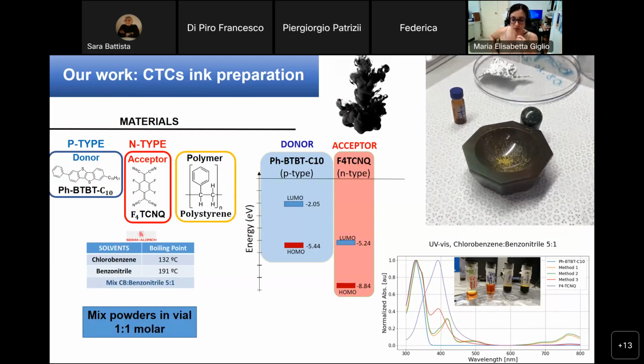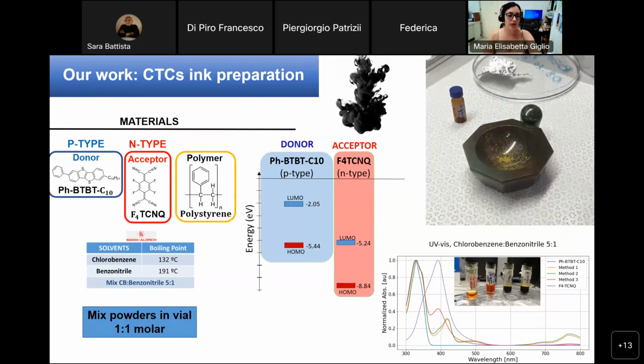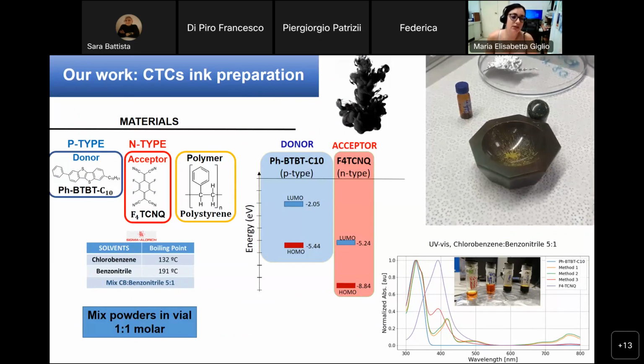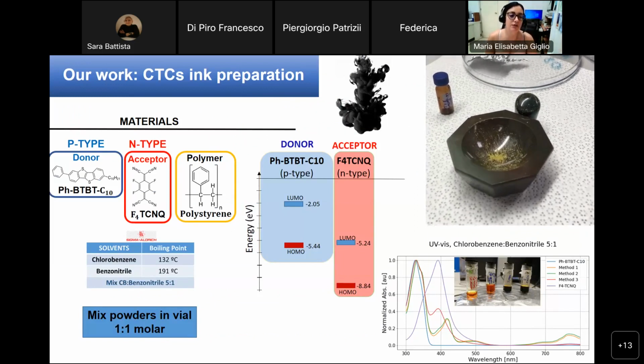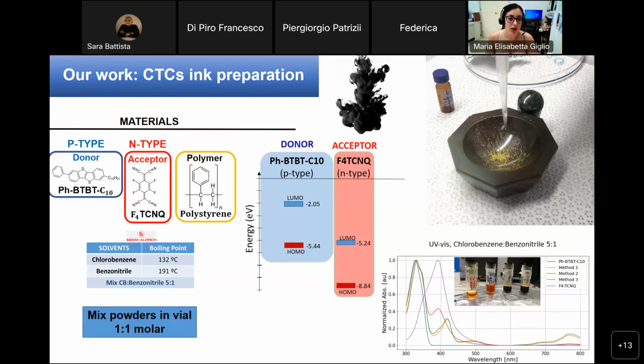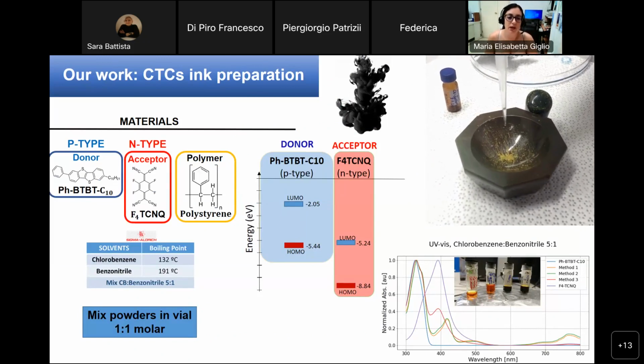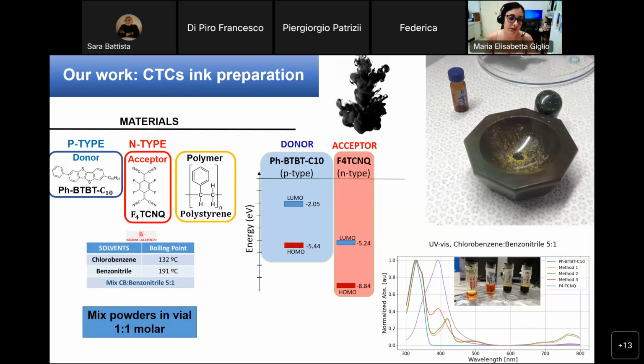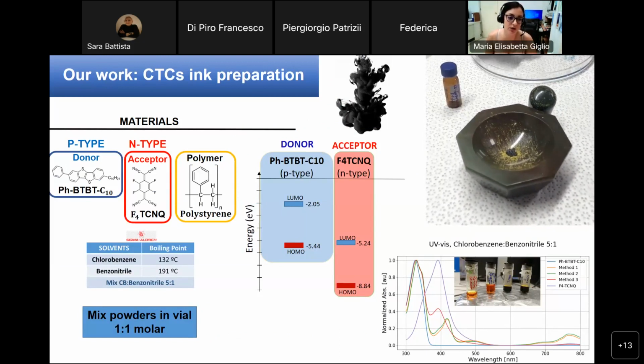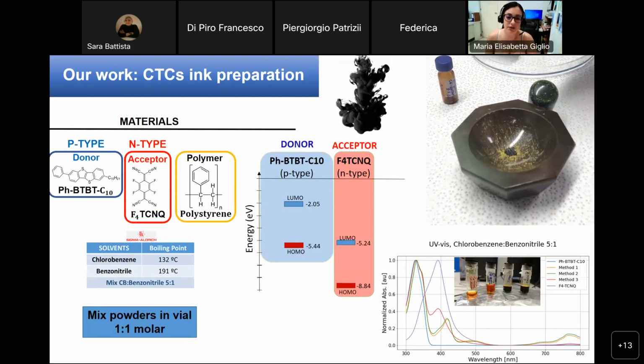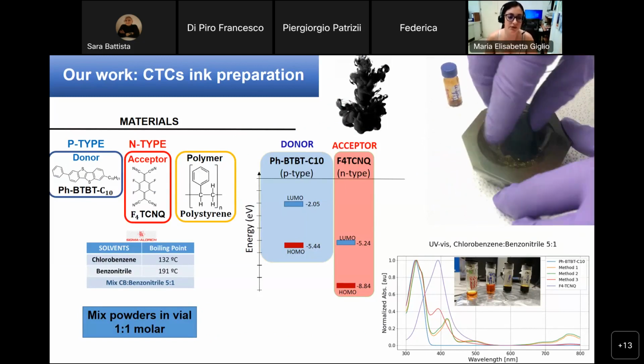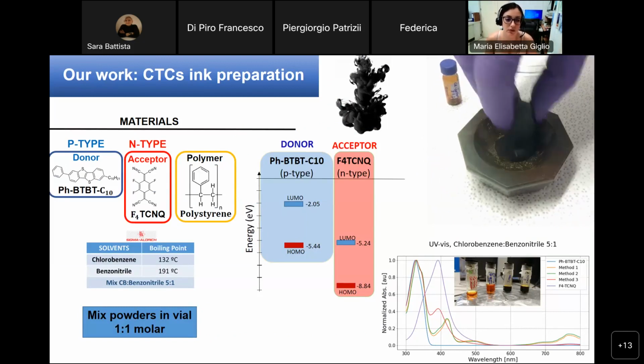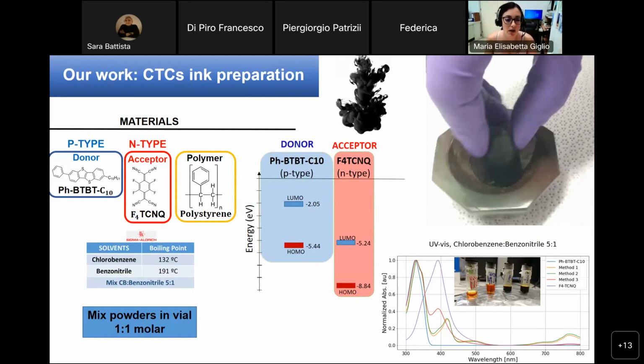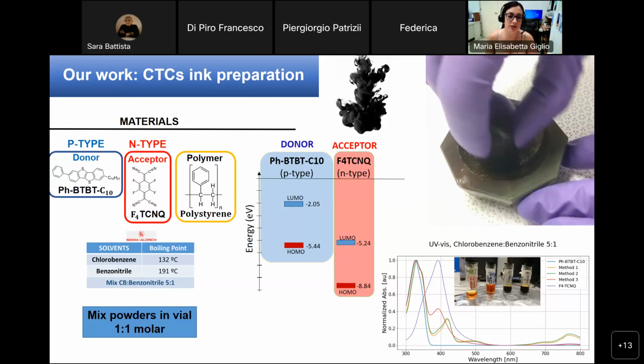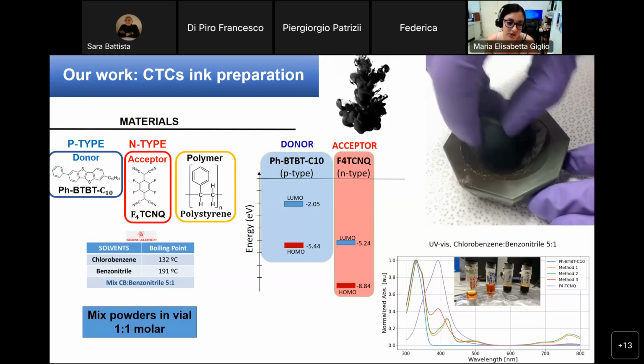So in the work I want to present here, we basically used the phenyl BTBT C10 as a donor and the F4TCNQ as an acceptor, blended with polystyrene in solution. And we use a mixture of two different solvents, chlorobenzene and benzonitrile, because the BTBT is very soluble in chlorobenzene, but the F4TCNQ is not very soluble in the same solvent. So we add benzonitrile, a solvent where we can easily dissolve the F4TCNQ.